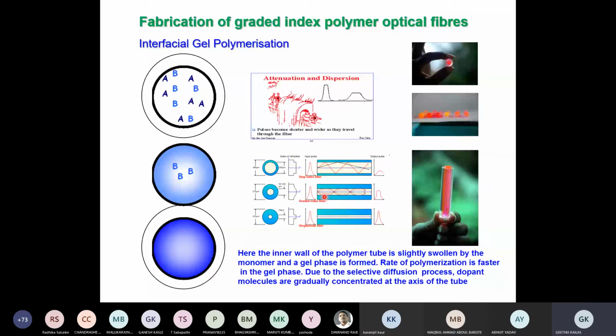So if you have a larger diameter fiber, it is always desirable to have a graded index refractive index profile in the core. So how to create a graded index structure? It is very easy to conceive an N1 and N2, like N1 in the core and N2 in the cladding. But what happens if you require a maximum refractive index along the axis, and it has to gradually come down to the cladding refractive index? Such an experiment can be done using the process called interfacial gel polymerization.